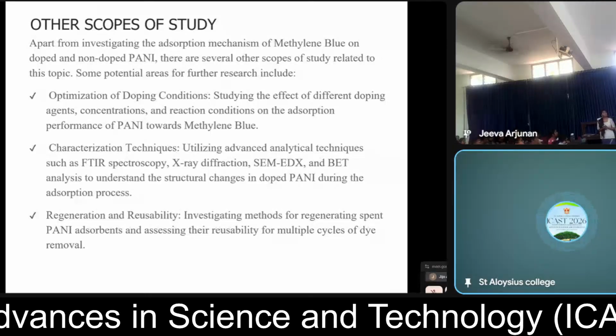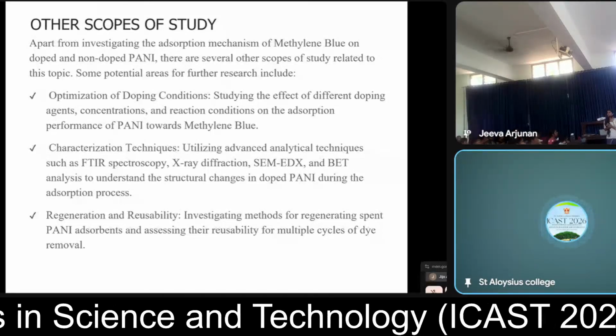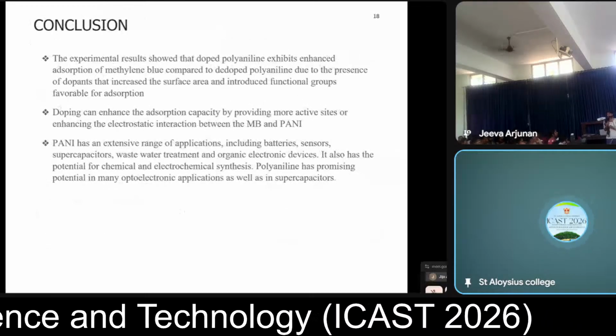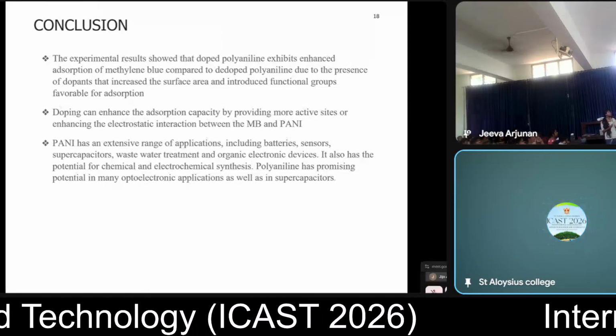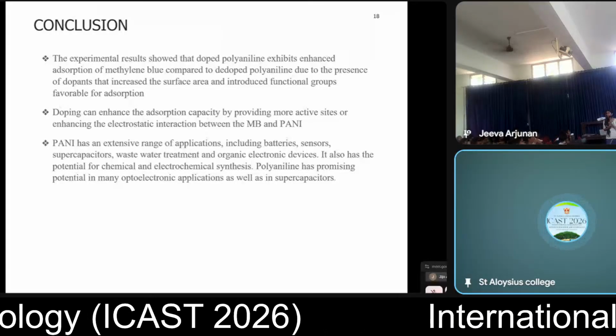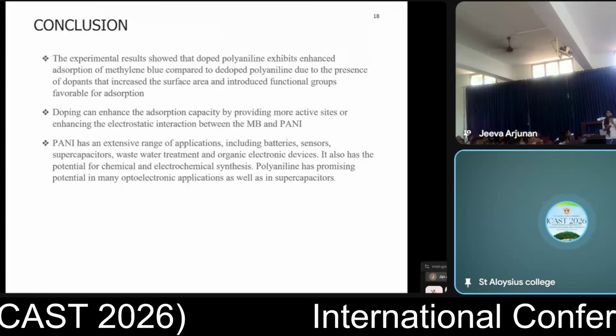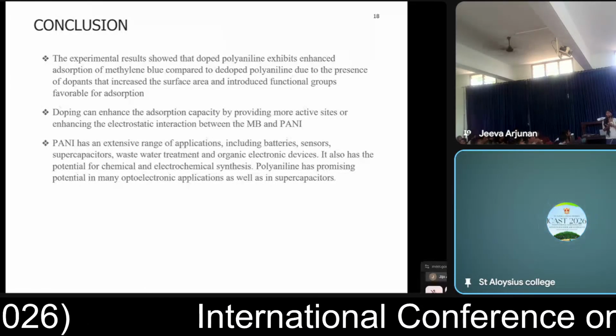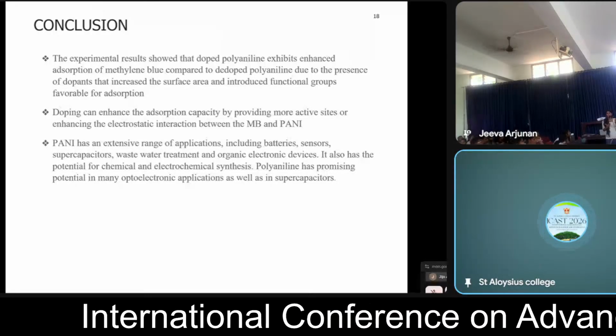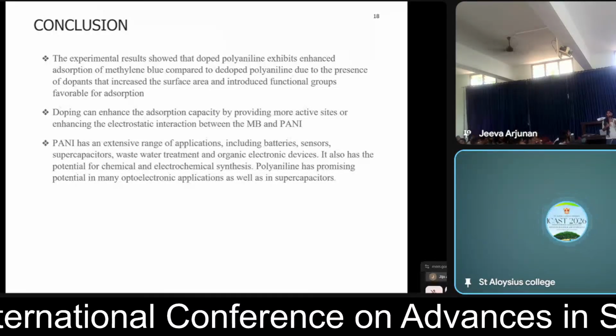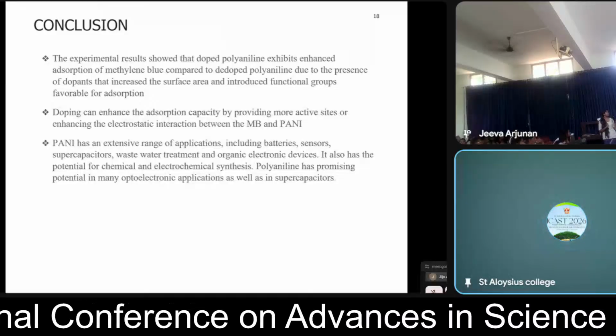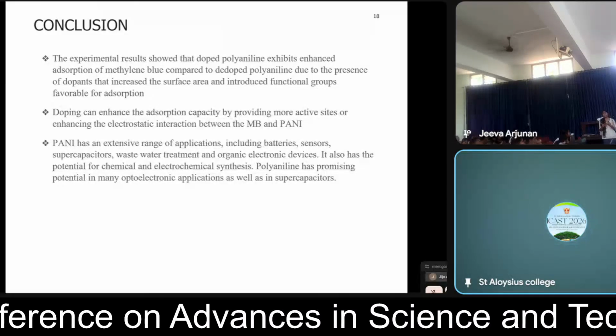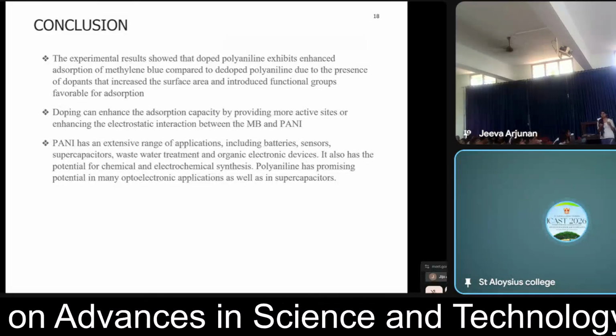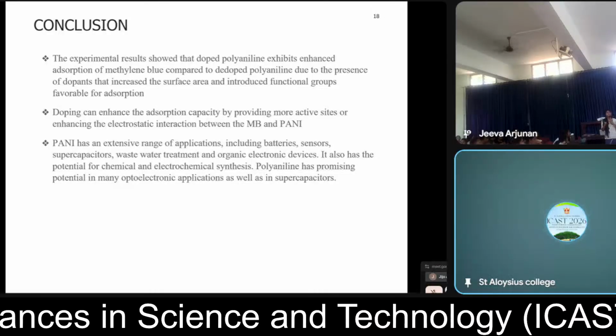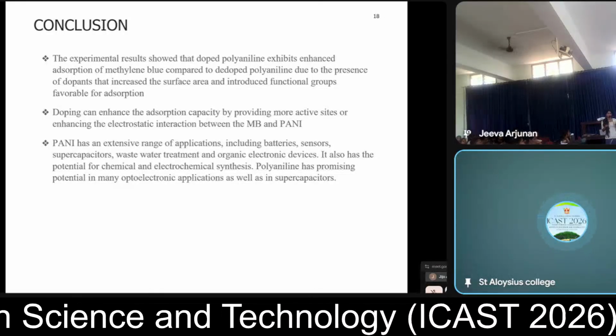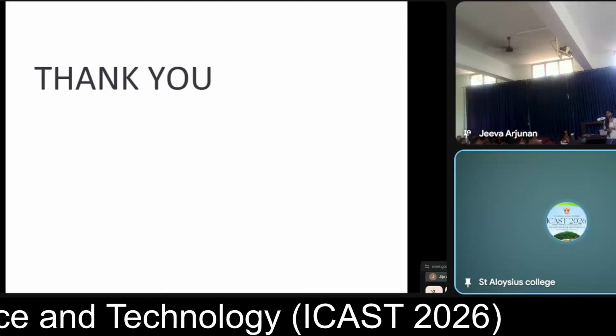By conclusion, from this experiment we got that doped polyaniline exhibits enhanced adsorption of methylene blue compared to the dedoped polyaniline. This is because the doping enhances the interaction sites and the availability of functional groups, which favors the adsorption. And PANI has extensive applications. PANI can be used for the removal of wastewater, and also due to its conductivity, we can use it in batteries and sensors, etc. Thank you.